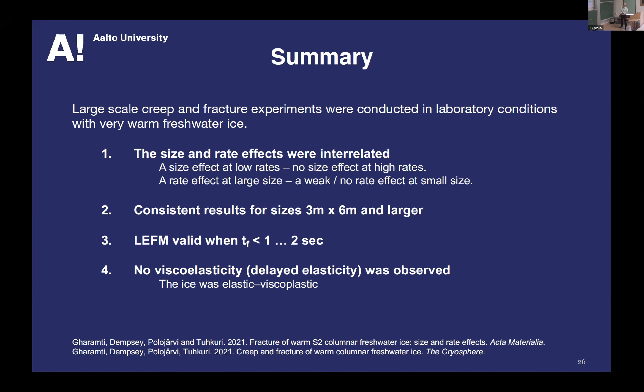Summary: Large-scale creep and fracture experiments were conducted in the lab with very warm fresh water ice. First result: size and rate effects are interrelated. Second result: consistent results for sizes from 3 by 6 meters and larger. LEFM is valid in our experiments as long as time to failure is below one to two seconds. No viscoelasticity or delayed elasticity was observed — the ice was simply elastic-viscoplastic.